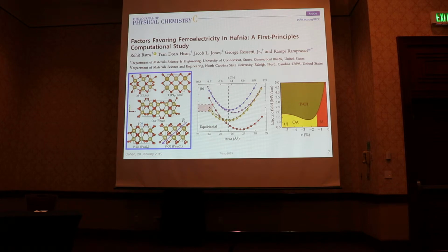Anyway, this paper really clarifies a lot of the issues that are present. And it doesn't seem to depend on what flavor of DFT you use. There's no flavor, as far as I know, that stabilizes the polar structure as a ground state under zero field conditions.